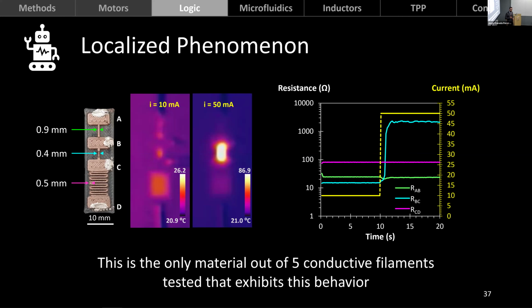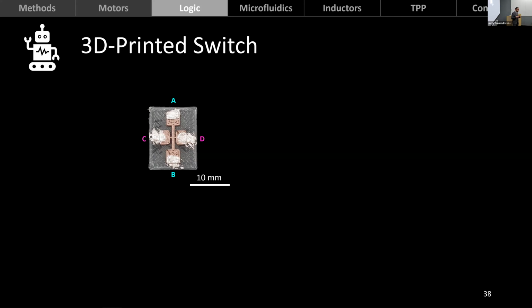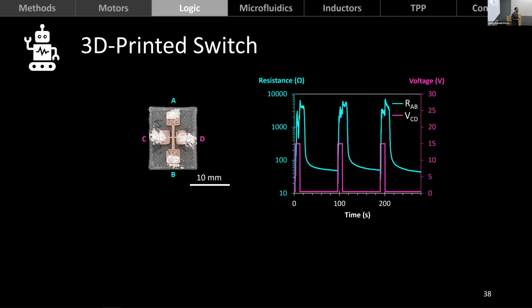power path allows the nominal flow of current. But if we apply high enough voltage across the control path, it triggers this spike in resistivity phenomenon at the intersection of both paths, effectively cutting the current through the power path. And we can actually see that through measurements. Here we see that when we apply a voltage to the control path, we can measure a spike in resistivity happening in the power path. So we are effectively capable of modulating resistance electrically.